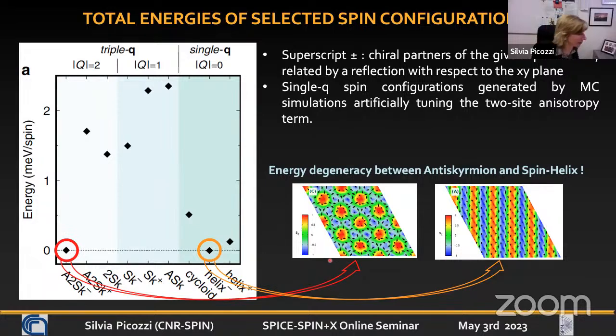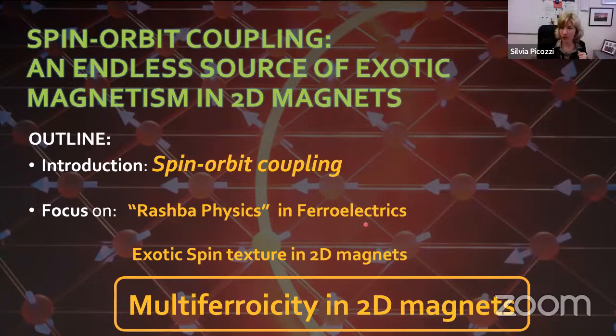But what I believe is correct and can be said is that anisotropic exchange in this kind of lattice and monolayer, in which you have heavy ligands like iodine, can give a sort of non-coplanarity. And as you will see in the rest of the talk, most likely this is the ground state and not this one. And so let me move to the final part of the talk, multiferroicity.